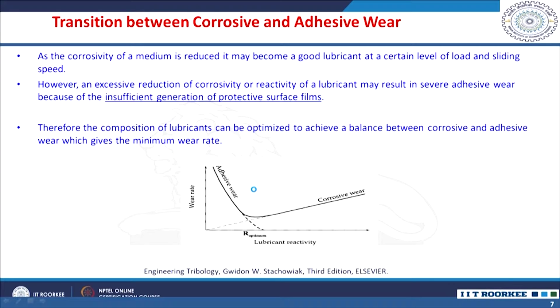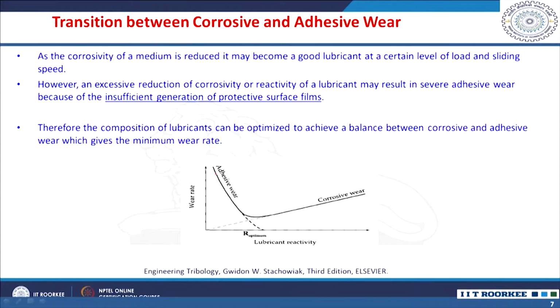So, as the corrosivity of the medium is reduced, it may become a good lubricant at a certain level of loading and sliding speed. However, an excessive reduction of the corrosivity or reactivity of a lubricant may result in severe adhesive wear, because of the insufficient generation of protective surface films.